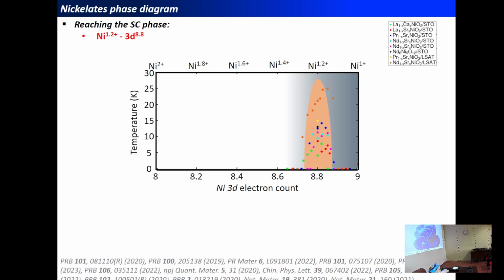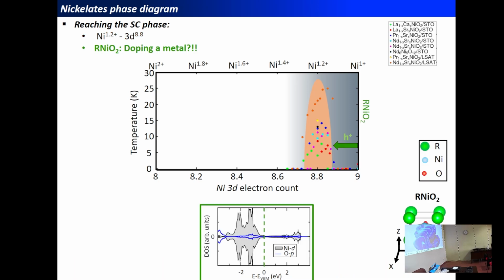So in order to understand superconductivity in the literature, people start from the RNiO2 member, which is just sitting over there. That's with a nickel in a 1+ formal oxidation state with 9 d electrons. And therefore, to reach the superconducting region, you have to create holes in the system. Nevertheless, if you look at the density of states associated with this material in the infinite-layer phase, you see that we have, in fact, a metallic material.